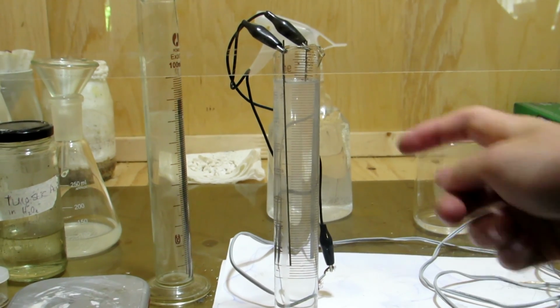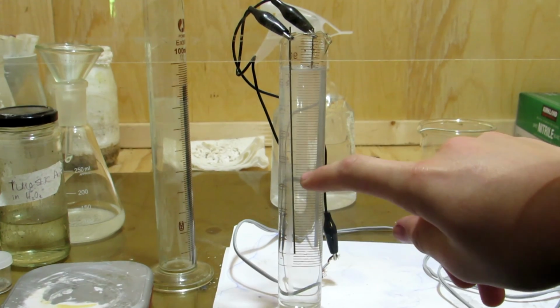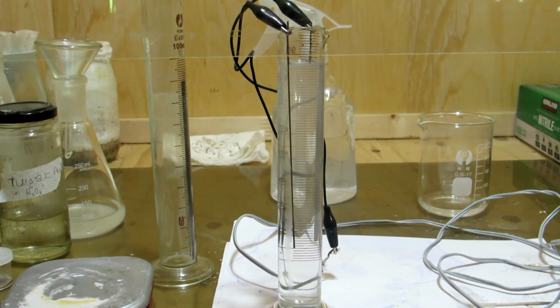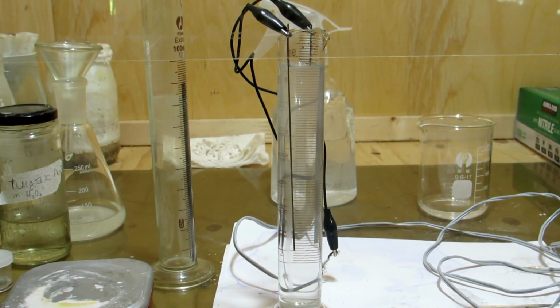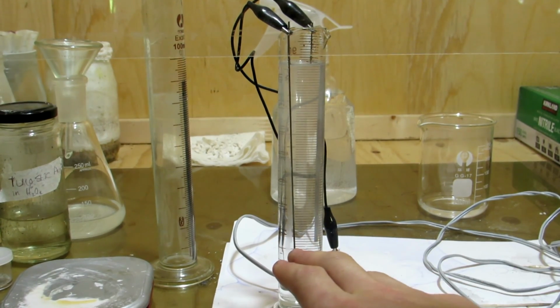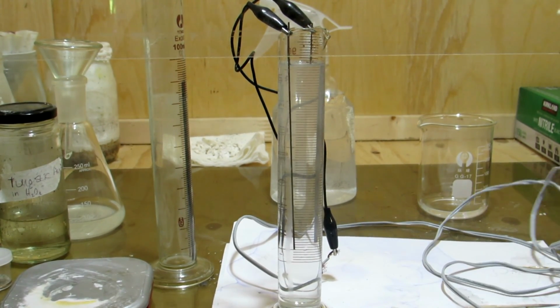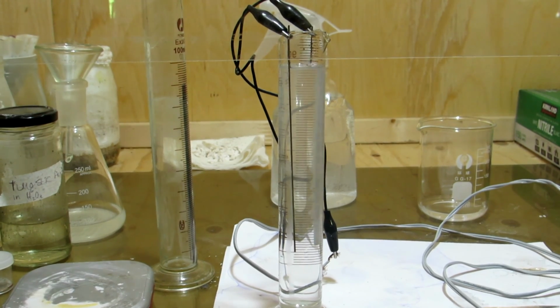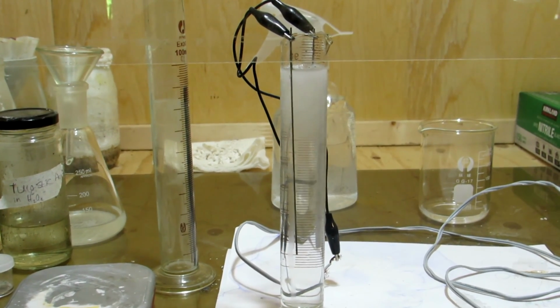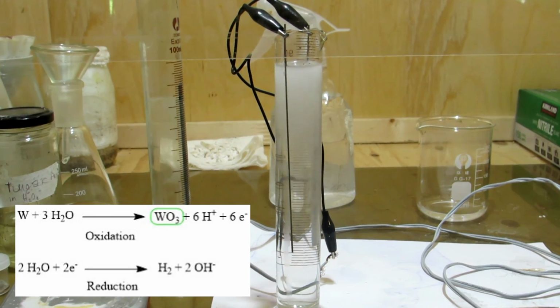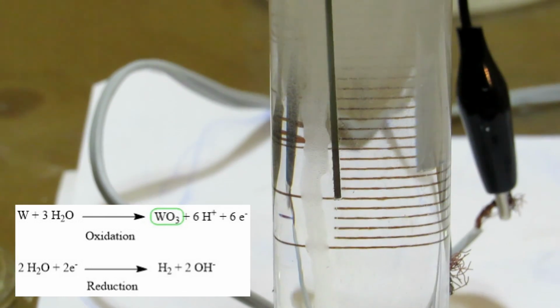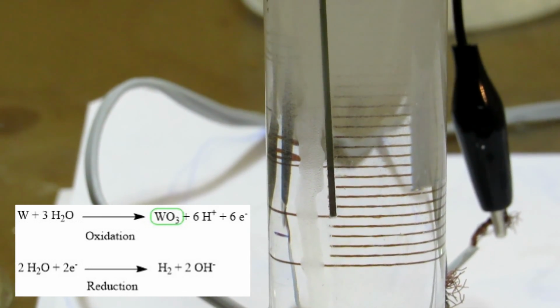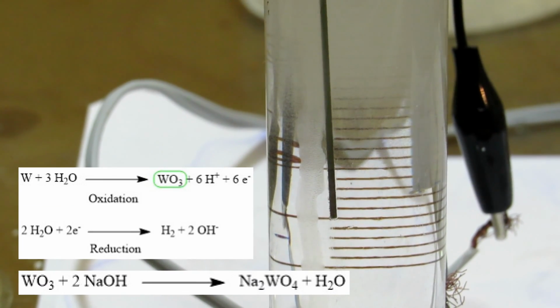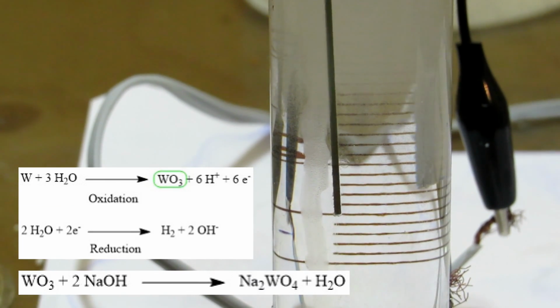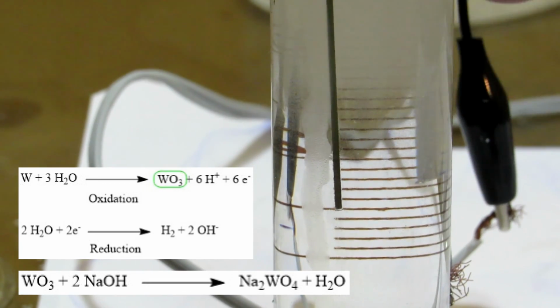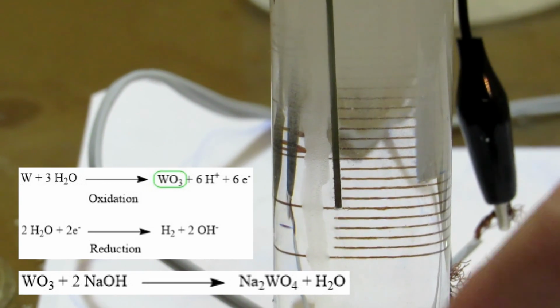To set up the apparatus, we can first use 2 alligator clips to attach 2 tungsten electrodes to the edges of the graduated cylinder. 20 grams of sodium hydroxide dissolved in 100 milliliters of water is then added to the graduated cylinder. The other ends of the alligator clips are attached to a 5-volt DC power supply to begin the dissolution. The vigorous bubbling at the negative electrode is hydrogen gas, while the density difference lines seen at the positive electrode are from sodium tungstate forming and diffusing away from the electrode. As a note, only the positive electrode will dissolve, so a non-tungsten negative electrode can be used.